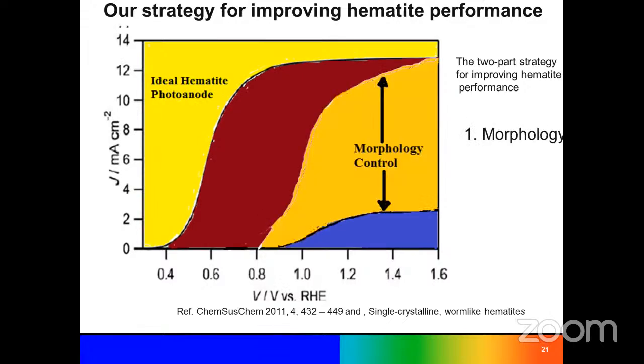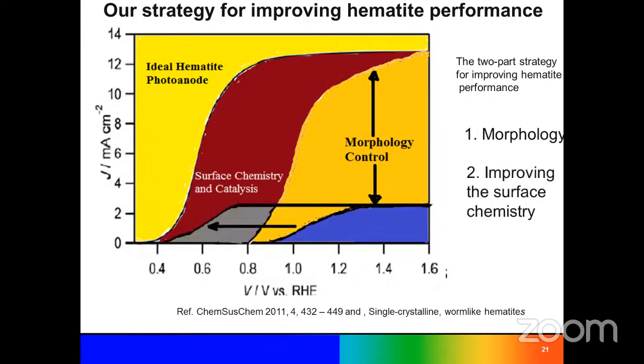So for this case, to increase the current density, we observe from the theoretical analysis that morphology tuning can improve the current density of the hematite material. So we tune different types of morphological structures, then apply them and check what current density we are getting. And then after reaching this current density, our target is to get the required voltage as low as possible. So for this case, the surface chemistry and catalysis is very important.